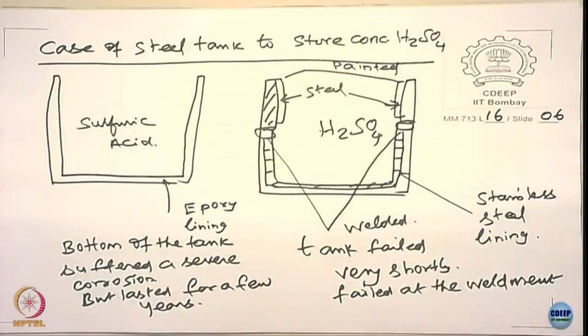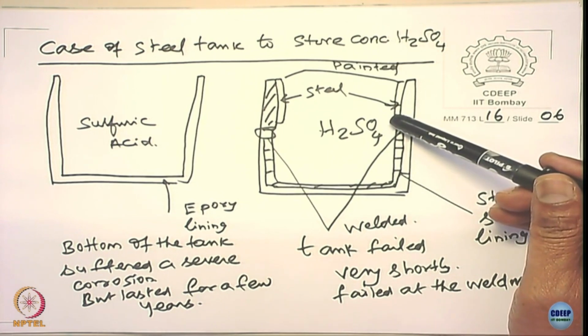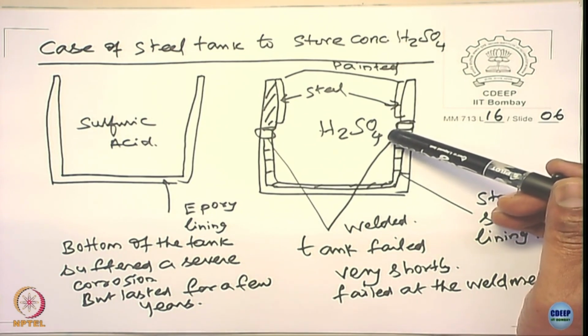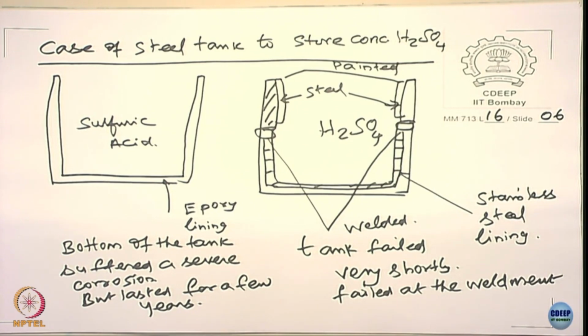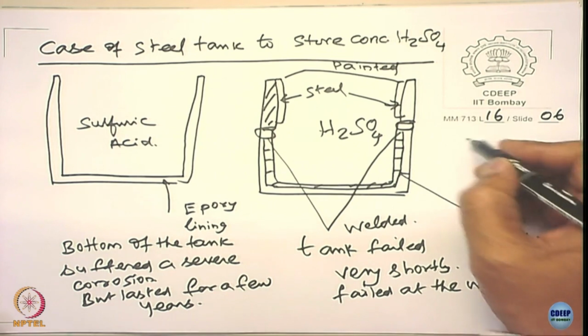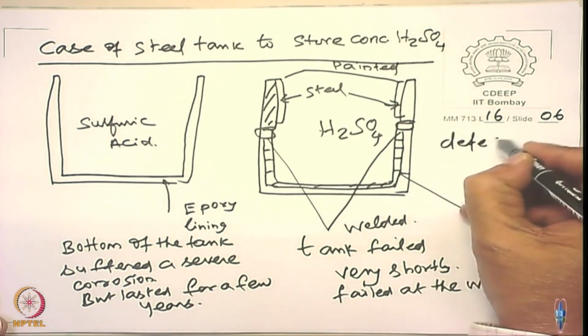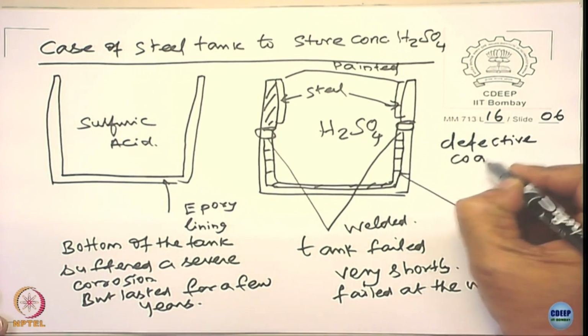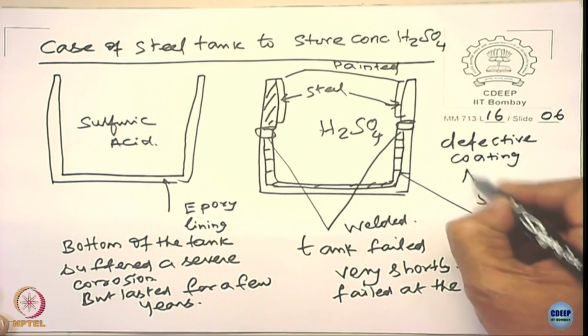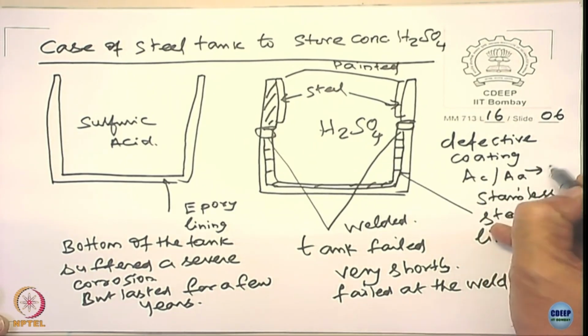When the paint is not impervious, it is porous. Now what happens? There are very finite places, small locations, where you have an anode. Not only that, you have a lining which is stainless steel, which is a cathode. That cathode is of infinite area compared to the very finite anode below the coating defects. So, very highly accelerated corrosion takes place, right. So, the reason is simple. What is the reason? The reason is, okay, defective coating, then what happens? You have AC upon AA tending to infinity.